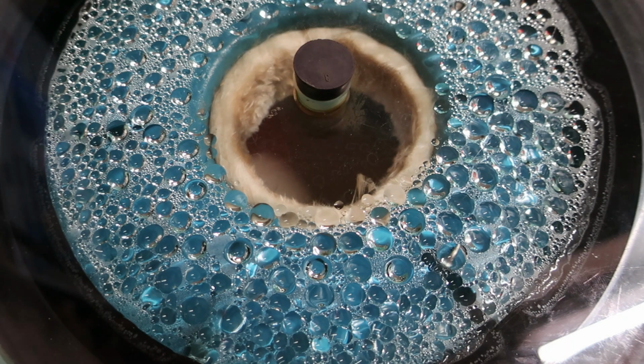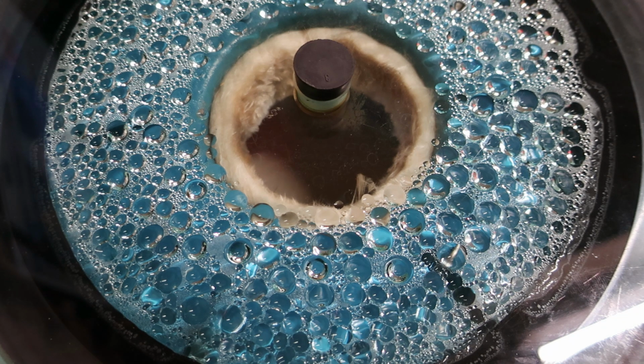So she's pretty warm in there, but the glass is still cold to the touch around the outside anyhow. We're about an hour in at full temperature and full vacuum. We have 1,786 grams, so 1.8 kilograms, close enough, right? What's that, 5 pounds of zeolite?